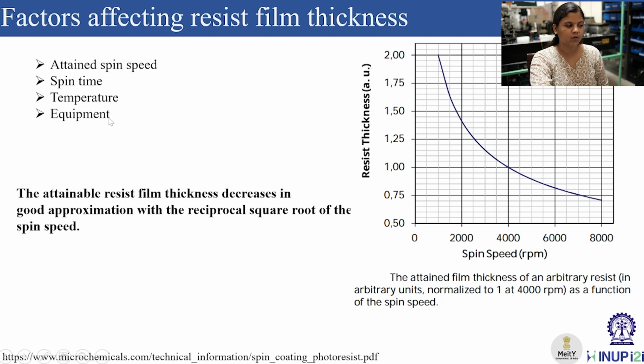The temperature and the equipment actually refer to the environment. If the temperature is more, that will lead to a faster rate of evaporation of the solvent, and hence the film will be thinner. By equipment we mean the environment inside the spin coater. If the air inside the spin coater is more humid, that will actually affect the rate of evaporation and hence our resist film thickness.